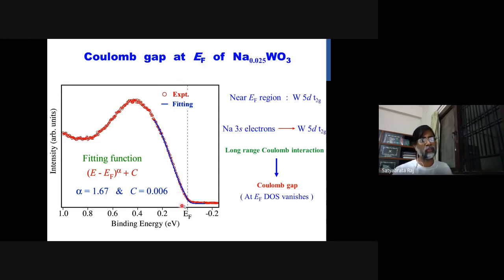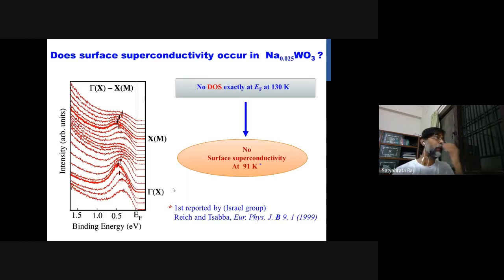arises. Soft because your EF has zero density of states, and as soon as you go a little bit lower than the EF, your density of states arises. So there is an Israeli group that claimed in 1999 that in the sodium tungsten bronze you can see a surface superconductivity at 91 Kelvin.